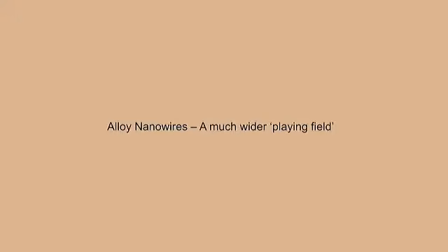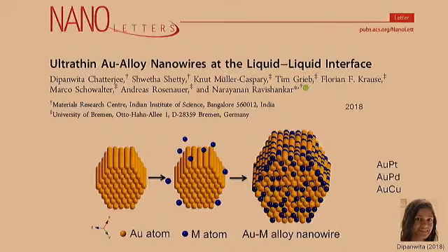So it turns out that for a very long time we could not. It turns out that the very, very fine balance between adsorption and desorption and things like that in gold is the only system that basically worked. More recently, we've been able to do things like platinum nanowires and, interestingly, alloy nanowires. We start off with the gold nanowires itself and then add a second element, and we can actually make alloy nanowires. Okay, this is also very interesting. Dipanita actually did this. Gold nanowires in the solution phase are unstable, and therefore we cannot directly do any alloying. So we have to keep it in a non-polar solvent where the gold wires are stable, and add the second metal through a polar solvent where it is soluble, and have the reaction happen at the liquid-liquid interface, basically, right? So this is something that we were able to do.